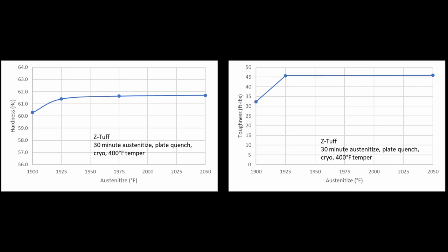So, if we do go higher, we get a little bit less carbide, maybe a little bit lower wear resistance. 1925's lower, so we can ensure that no grain growth occurs. But it does look like that 1% vanadium is effective in keeping the grain size small, even up to 2050 degrees.